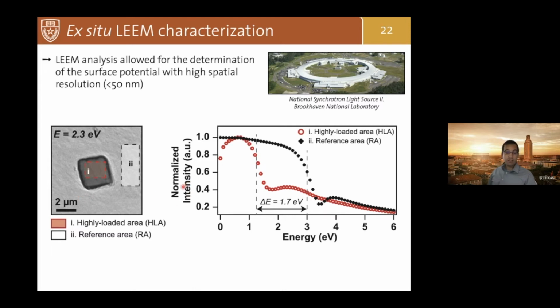The low energy electron microscopy measures the surface potential by looking at the intensity of reflected electrons as a function of electron energy. The inflection point here is a clear indication of where the surface potential of our sample is. And what you can see in this slide is a clear difference between the IV curve extracted from the region outside this highly loaded scan region and the region inside, meaning that in the region inside, where we apply high load, there is a completely different surface potential. So how can we put all these together?